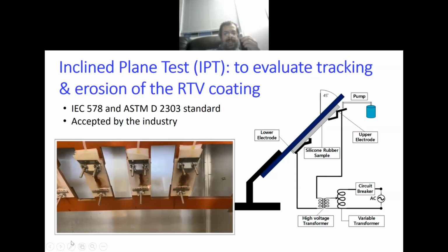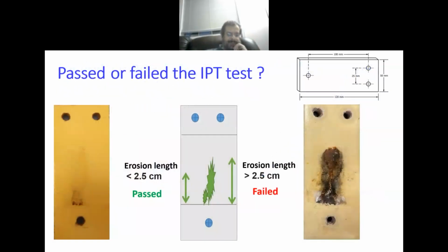And then you will have a high voltage here, and this will be a ground end. So now you have a high voltage, you have a ground, you have an electrolyte, then you will start to have arcing. We do the test with a certain protocol, and we'll talk about the criteria of fail and pass in the coming slides. We keep this for around 6 hours, and then we check if the material is good or not. There is a standard test at 4.5 kV, and we keep the testing running for 6 hours. Next, please.